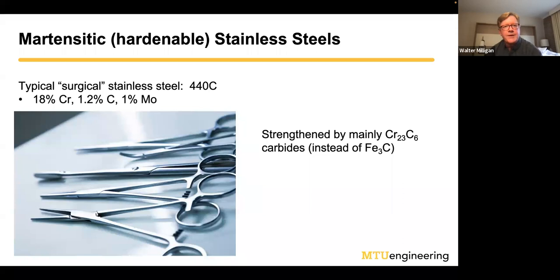So we'll talk about the martensitic stainless steels first. The most common one that you'll come across if you work with these things is a steel called 440C. If you try to buy something online and they call it surgical stainless steel, this is usually what they mean. So you can see the composition up here. This has 18% chromium. That means it's much more expensive than plain carbon steels because chromium is expensive. It's got pretty high carbon, more than the 0.8%, and it's got a little molybdenum in there for heat treating purposes.